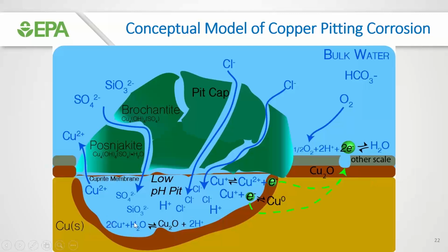pH can drop quite a bit because as copper 1 is being produced in the pit itself through hydrolysis and formation of cuprous oxide, I should say, you release H+, so the pH gets quite low. And we know this for a fact. I measured the pH of water coming out of a pit, and it can be quite low. Electrons are transferred across the copper out to the cathode, where it interacts with the oxygen or chlorine or other disinfectant, and as a result, pH can tend to go up at the cathode.